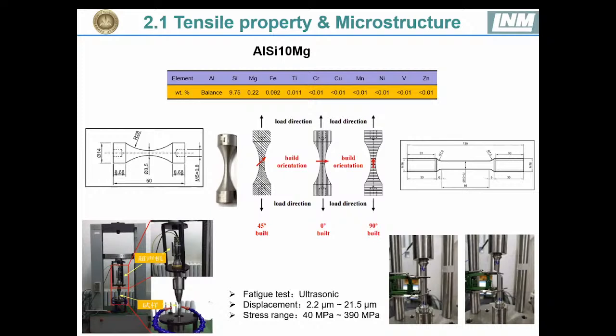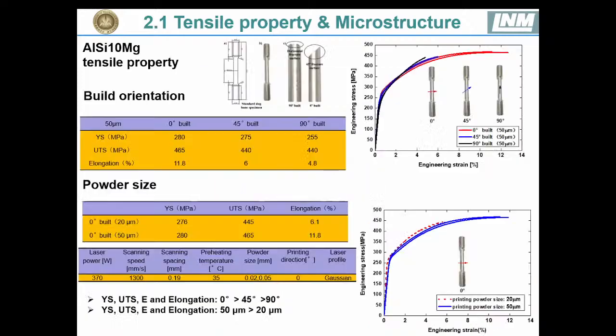For this specimen, we can see the hourglass shape specimen is used for the ultrasonic fatigue test. The frequency of this machine is 20,000 hertz. During the test, air is pumped to cool the specimen in order to reduce the heating. Displacement loading is applied, and the stress range is between 40 megapascal and 390 megapascal. The right picture shows the specimen for the tension test.